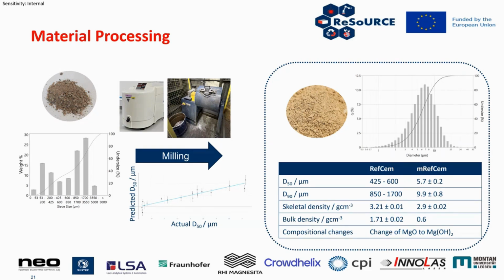We reduced the skeletal density and the bulk density slightly. So the bulk density is just explained by there being more voids when we reduce the size of this material, which is expected. And the skeletal density is due to us changing some of the magnesium oxide to magnesium hydroxide, which has a lower density. And we also see this in the compositional changes. So when we look at the XRD, we can see that we've created some magnesium hydroxide from the magnesium oxide.